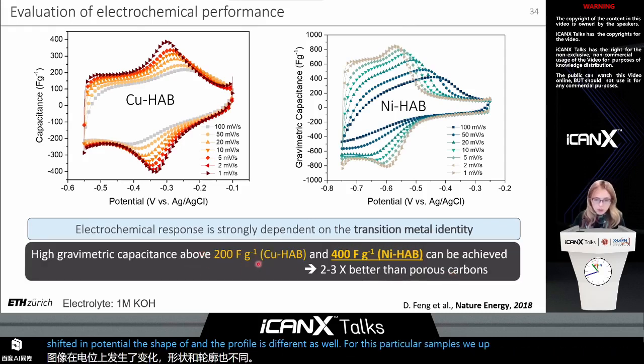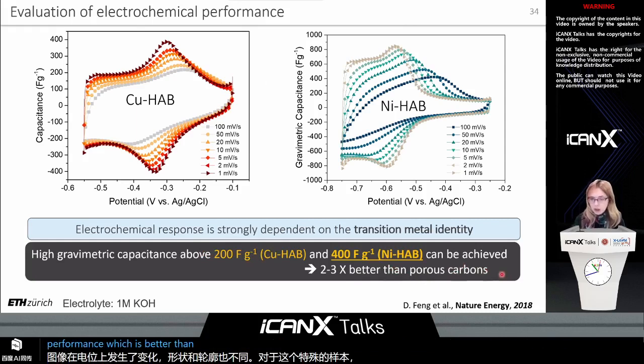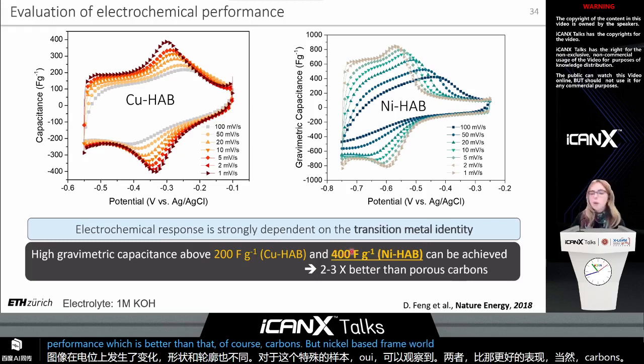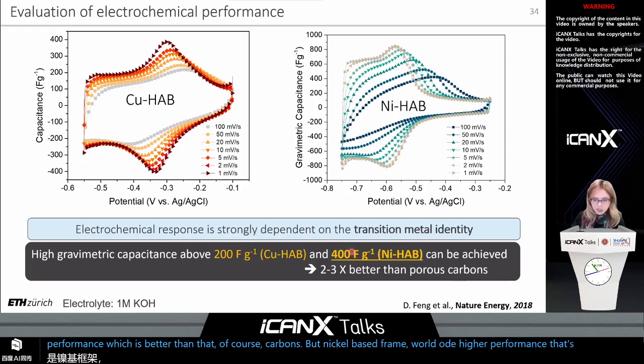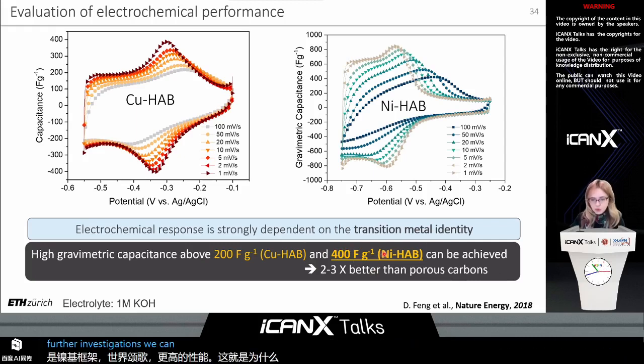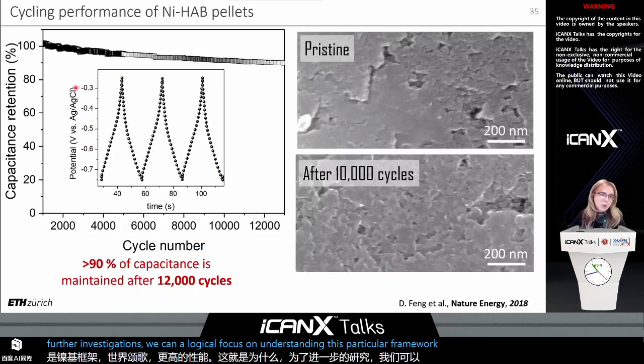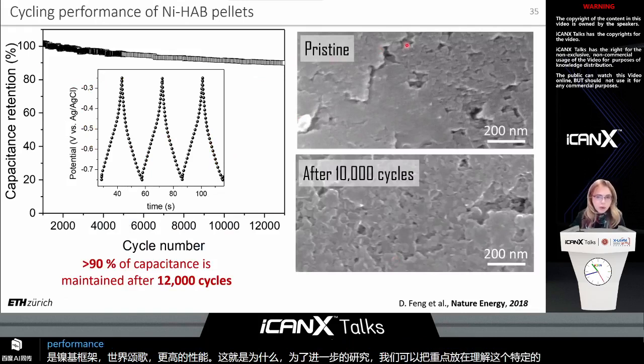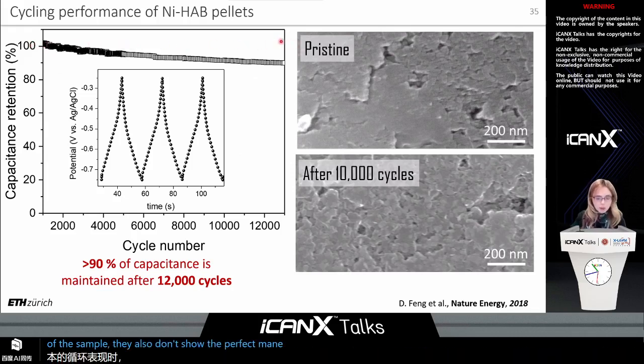We observe for both of them the performance which is better than that of porous carbons, but nickel-based framework showed higher performance. That's why for further investigations we had more detailed focus on understanding this particular framework. And when we look at the cycling performance of this sample, they although don't show the perfect maintenance of the capacitance, but it is pretty good for this new family of the supercapacitor materials, with more than 90% of the performance maintained after 12,000 cycles.